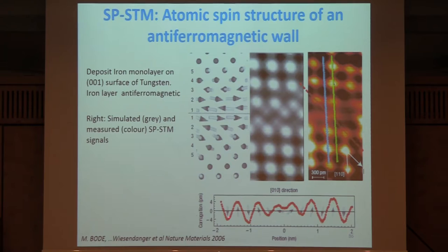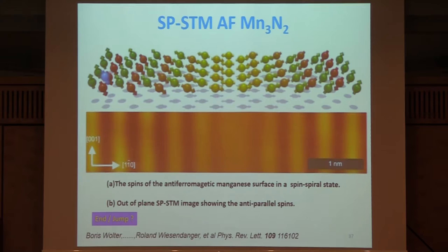Okay, so you can actually very convincingly image domain walls in this material. So here's the magnetic signal varying, and then you can see the moments are tilting over. There's a better one here where they just average the intensity along the rows in that scanning direction. And they think what's happening is, you see this up, down, up, down, but it's turning over, and again, it's a domain wall like state. Well, this is more complicated. This is actually a spiral state. It's not an accidental domain wall.